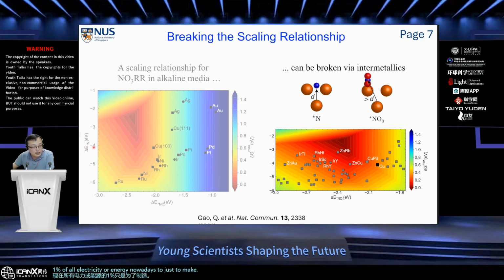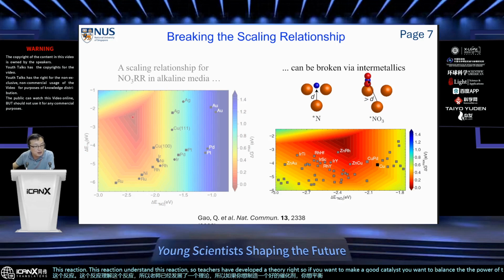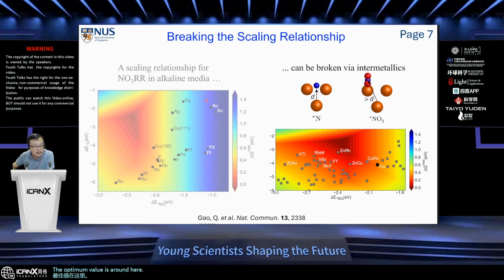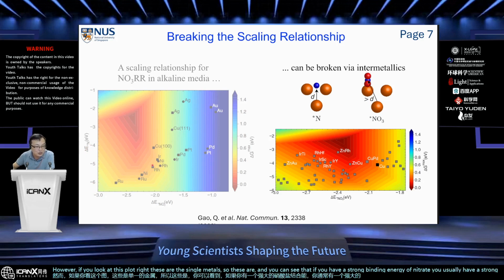To understand this reaction, theoreticians have developed a theory. If you want to make a good catalyst, you want to balance the power of the catalyst to bind the nitrogen species as well as the nitrate species. The optimum value is around here. However, if you look at this plot, these are the single metals, and you can see that if you have a strong binding energy of nitrate, you usually have a strong binding energy of nitrogen species. This is the so-called linear scaling relationship. So no matter what metal you use, you cannot really reach the optimum value.